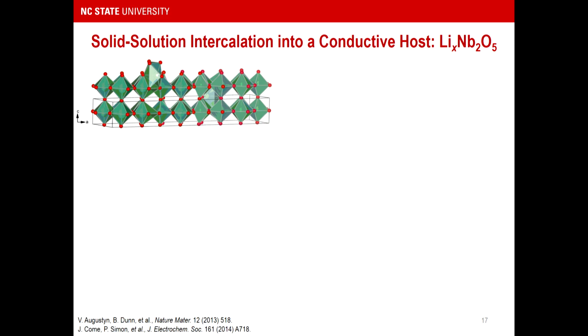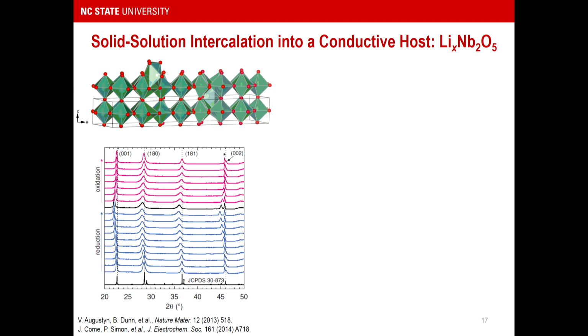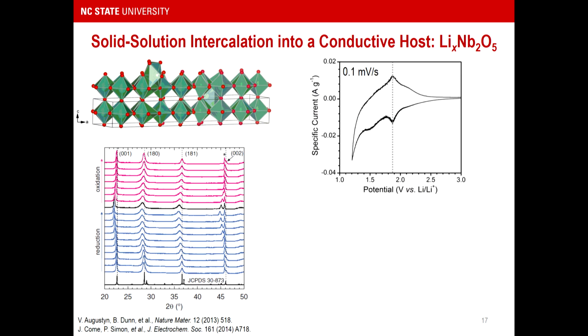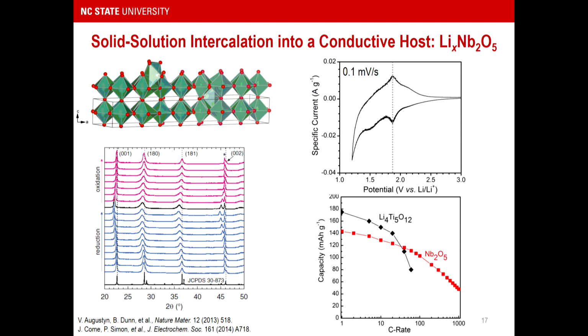So recognizing that structural stability is key, we found that indeed if you have a conductive host, like niobium oxide, when it becomes lithiated, that undergoes a pure solid solution intercalation mechanism, which is what we measured with in situ X-ray diffraction. You get cyclic voltammograms of this material now that actually begin to look like mirror images with these redox peaks being superimposed right on top of each other. That large cathodic peak that you see at the lower potentials here is due to the electrolyte decomposition, an irreversible process. And again, thinking about even the potential of intercalation reactions as being limited by surface processes is very important in pushing ultimately the power capability of these materials.